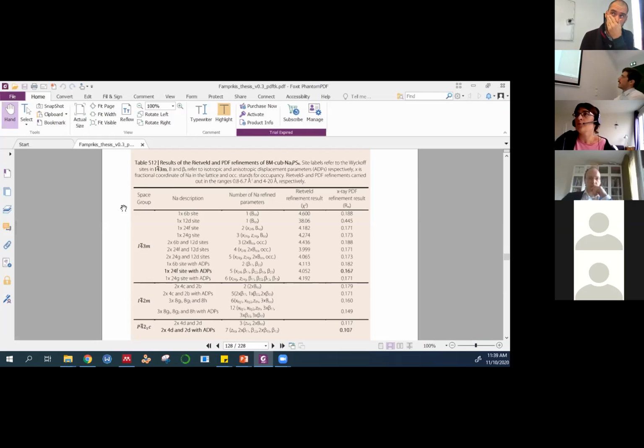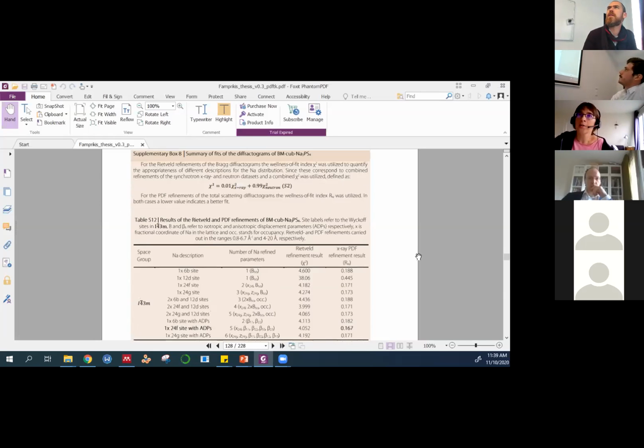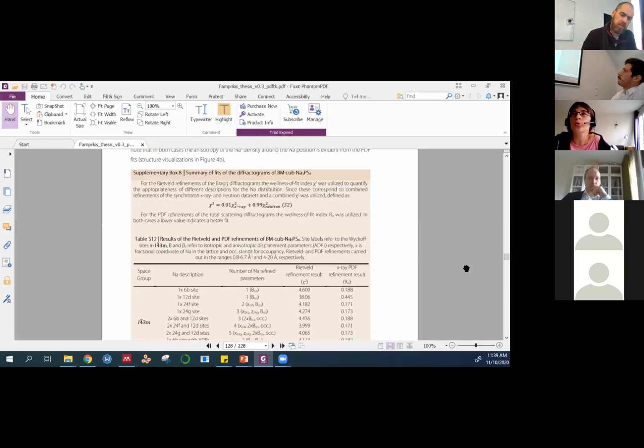Yes, I understand. All these refinements, I think it's written just above, were done using combined neutron and XRD patterns. Yes, just above your table S12. And you use a criterion which is 1% of X-ray and 99% of neutrons. So basically you're doing a refinement of the neutron pattern, and you don't care about the X-ray pattern.